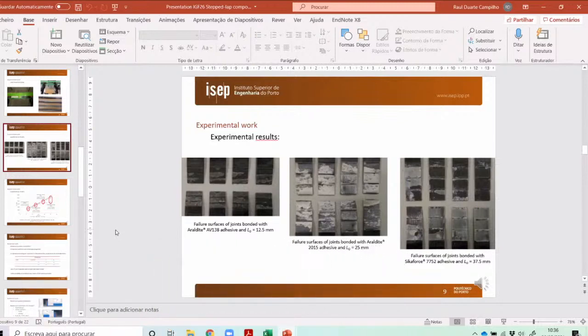Yes, exactly. The main reason is that for the 2015, we have a cohesive failure, but we have a visible layer of adhesive on both sides. For the 7752, the failure is also cohesive, but we need to check very closely to see a very thin layer of adhesive in the black portion. It is still cohesive, but it is near to one of the interfaces. We usually get this type of failure when we have a very ductile adhesive.